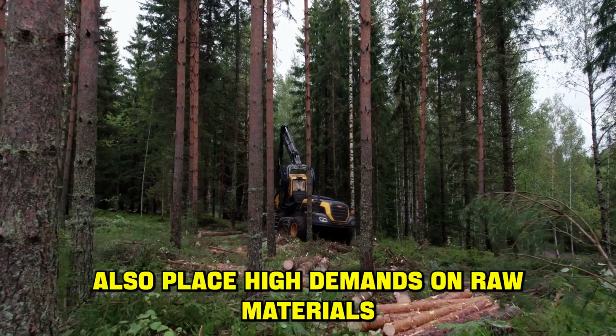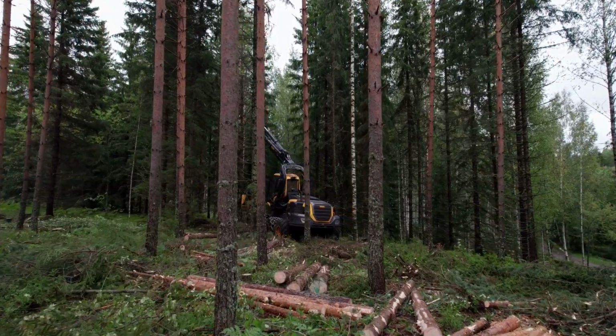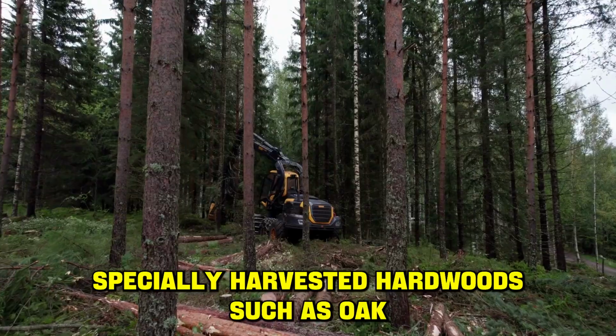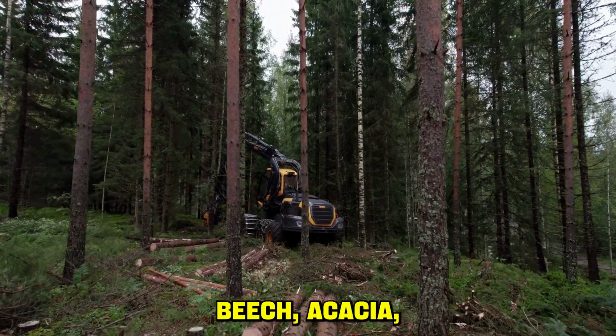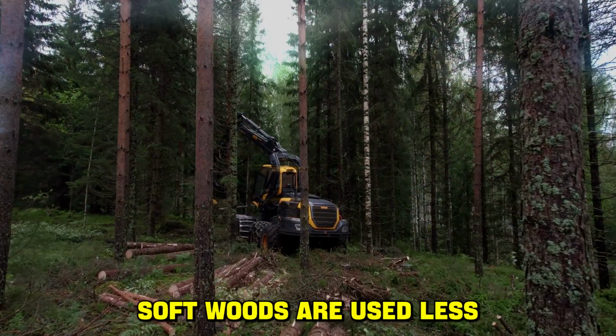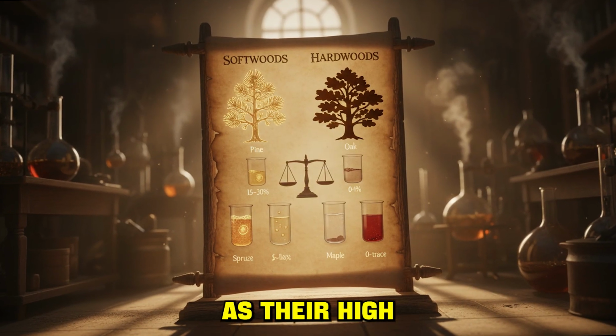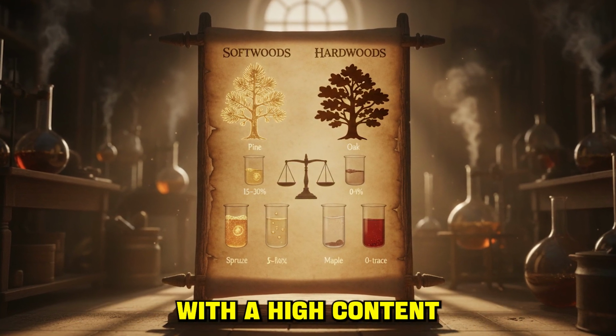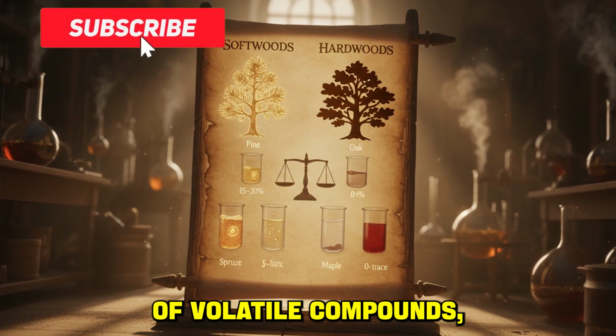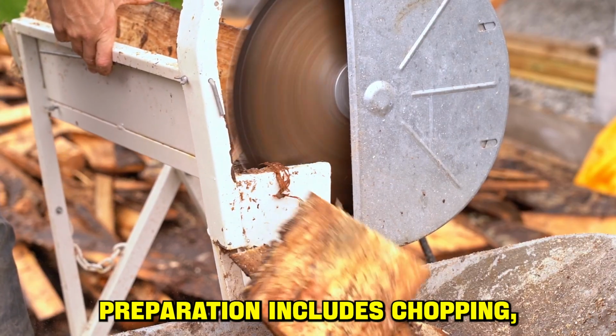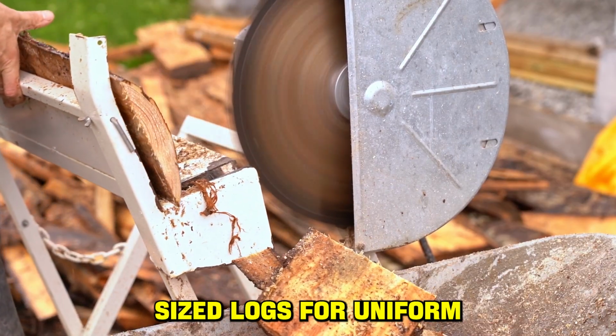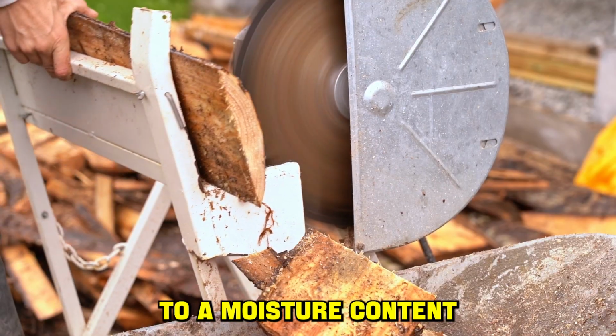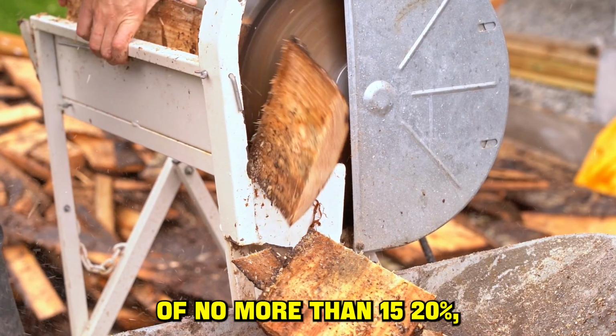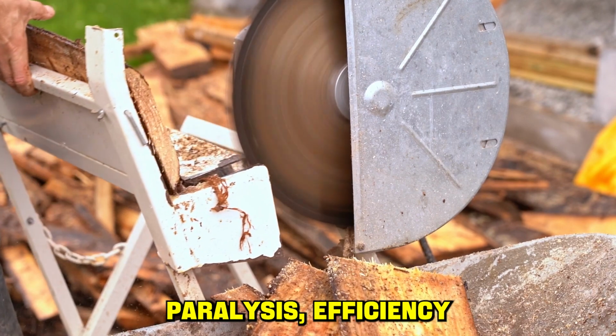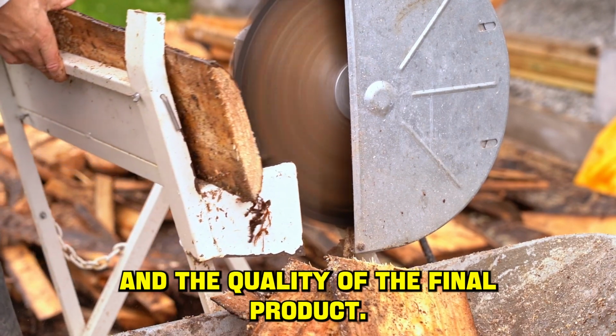Modern technologies also place high demands on raw materials. Specially harvested hardwoods, such as oak, beech, acacia, hornbeam, and birch are used. Softwoods are used less frequently, as their high resin content produces charcoal with a high content of volatile compounds, which sparks and has a distinctive odor. Raw material preparation includes chopping, splitting into standard-sized logs for uniform heating, and mandatory drying to a moisture content of no more than 15–20%, which dramatically improves pyrolysis efficiency and the quality of the final product.